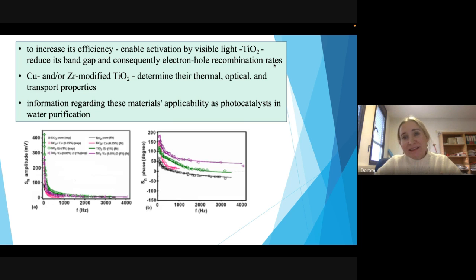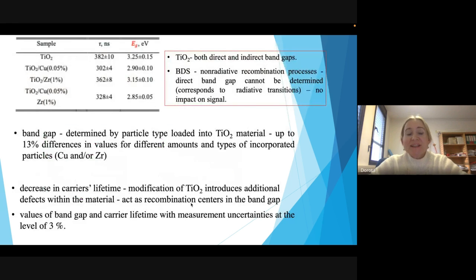The titanium dioxide is doped by the use of different molecules, and surface sensitization is performed. What we did in our analysis, we modified titanium dioxide using copper or zirconium molecules. We performed the standard measurements of the amplitude and phase of the signal as a function of modulation frequency. We used our theoretical model and fitted it to the experimental data to extract information about the energy bandgap and carrier lifetime of such modified material.